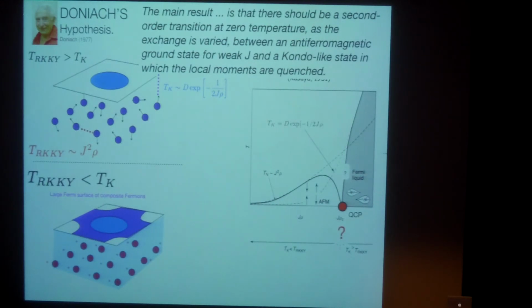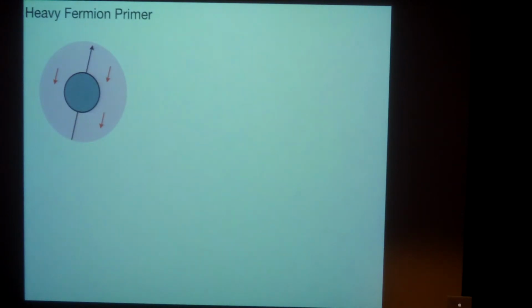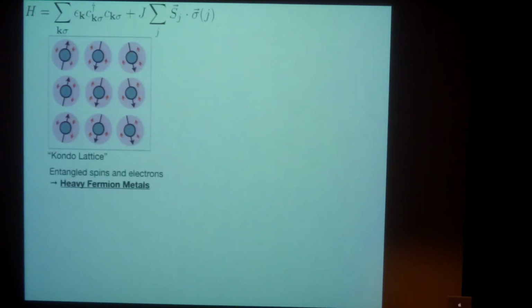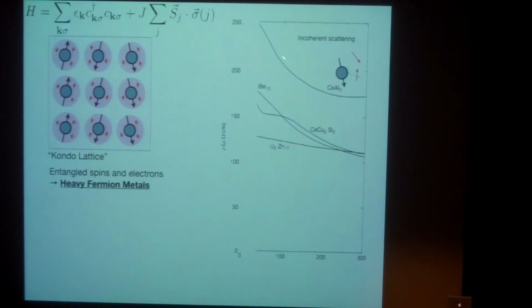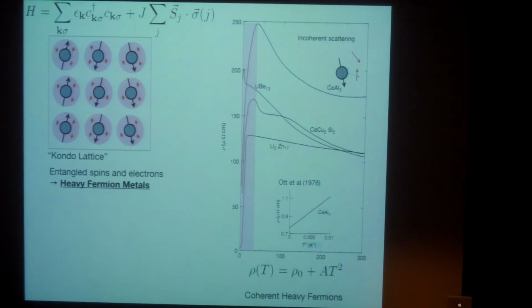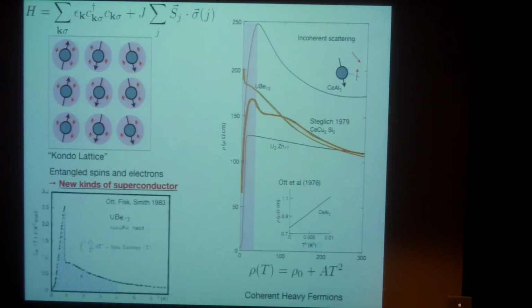So that's the end of my cartoon introduction, but I want to point out that empirically, this entanglement takes many forms. And one of the things you can see is that it leads to the formation of heavy electron metals. And you see that because the resistivity doesn't continue to rise indefinitely, coherence develops, and you form metallic behavior. Cerium aluminium-3 is one of the classic examples. But there are other kinds of entanglement, for example, new kinds of superconductor. Uranium beryllium-13, although discovered in 1983, remains an unsolved problem of superconductivity, mainly because this large area of entanglement here that forms the superconductor is spin entanglement. It raises the question, how do spins entangle to form superconductors?